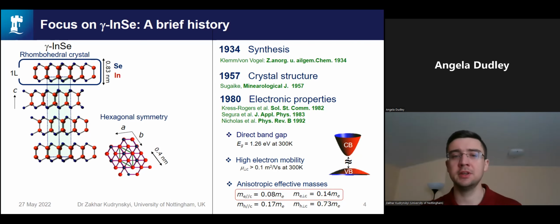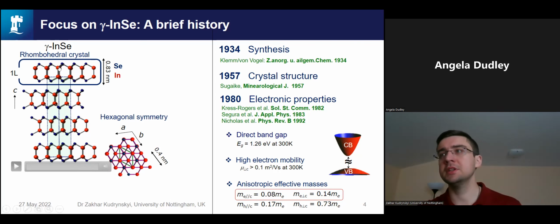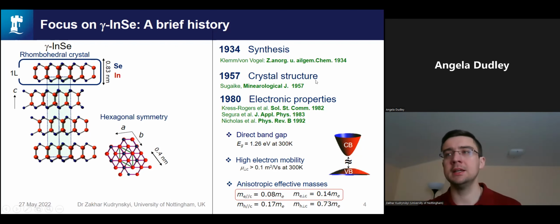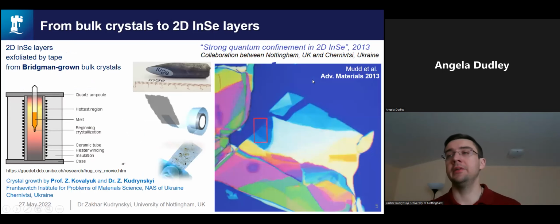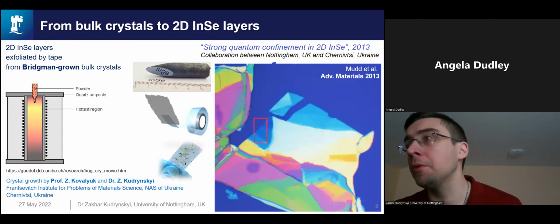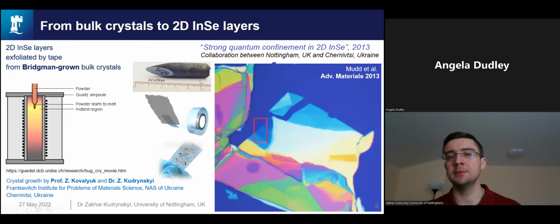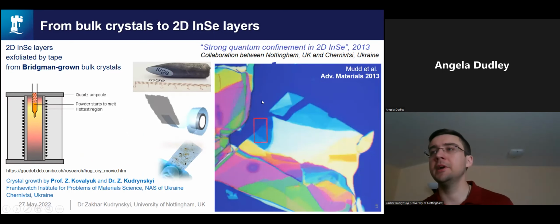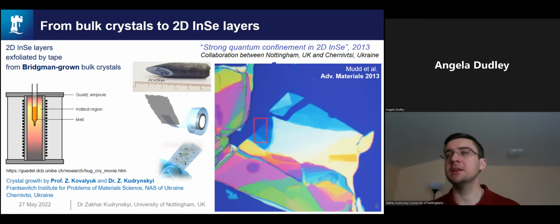Here you can see a single stoichiometric layer with a thickness of just 0.8 nanometer, and it consists of 4 layers of indium and selenium atoms. In the bulk form, it's a direct bandgap semiconductor with a gap in the near infrared region and high electron mobility. I started working with this material as a PhD student in Ukraine. There we were growing these bulk crystals of indium selenide by the Bridgman method. And then in collaboration with colleagues from Nottingham, we started mechanically exfoliating these bulk crystals down to few layer nanoflakes.